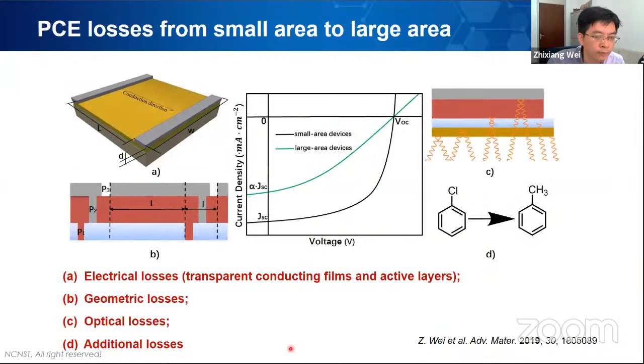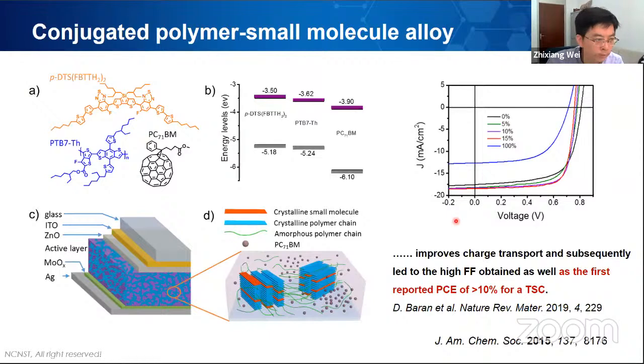So this kind of decrease comes from different kinds of losses. For example, there are electrical losses from the transparent conducting film and also the active layers, and also geometric losses due to dead area that does not contribute to the efficiency, and optical loss mainly because the films are not uniform. And also some additional losses. For example, in the lab scale, you can use some really poisonous solvent, but for the industrial scale, you need to use a green solvent. At least you need to use toluene or xylene as a solvent, not chlorobenzene. Yeah, with this, the efficiency normally decreases a lot.